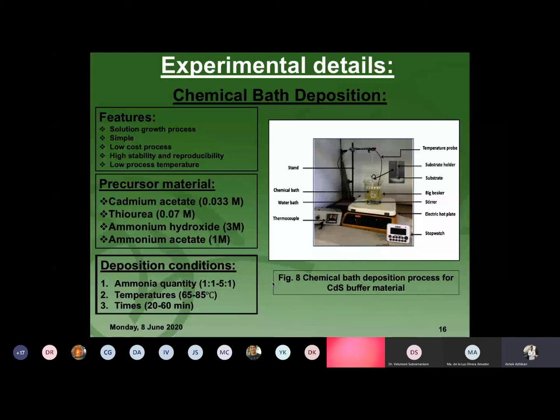The various precursor materials used for the CdS deposition include cadmium acetate as the cadmium source, thiourea as the sulfur source, ammonium hydroxide as the complexing reagent, and ammonium acetate as the catalytic reagent.